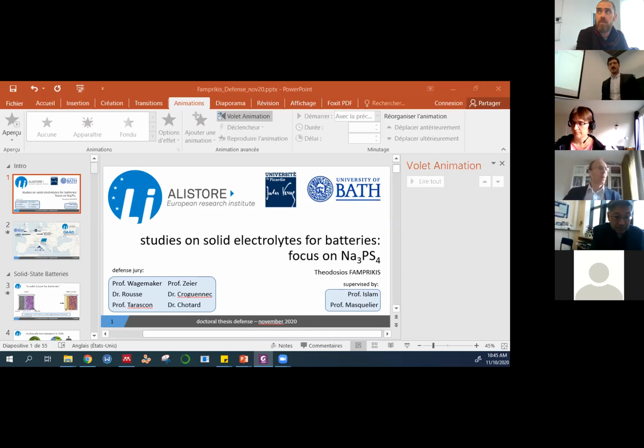Maybe starting with the structure determination of the Na3PS4 for your discovered gamma phase. So already from all your efforts, it shows it's a very challenging structure refinement. And you play a number of tricks, but you actually use a single PS4 configuration. But then I think, if I understand correctly, you use several sulfur positions, and that allows you to have several anisotropic displacement parameters to kind of capture the sulfur mobility. So far, is that correctly understood?